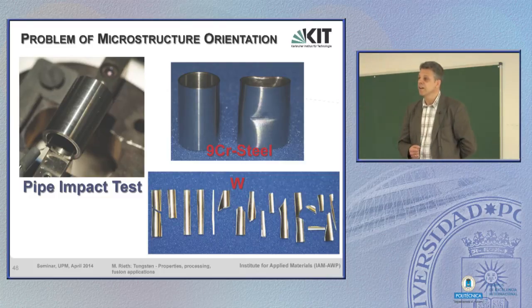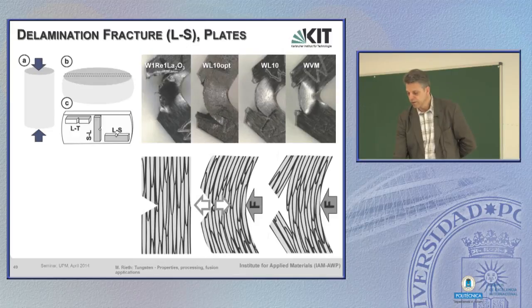That doesn't work with tungsten rod material, and this is simply due to the microstructure and due to the unfavorable orientation of the grains here. So that's useless. Delamination fracturing plates look similar. You see it here. Also crack evolution not perpendicular through the specimen, but along the rolling direction.